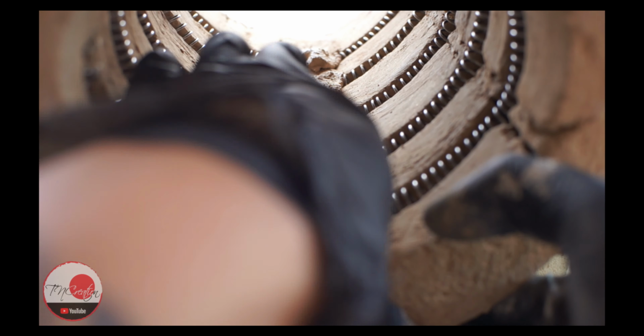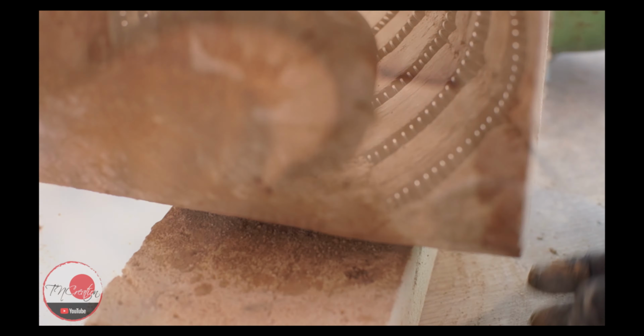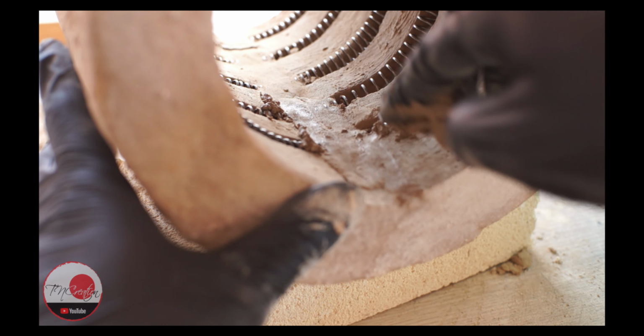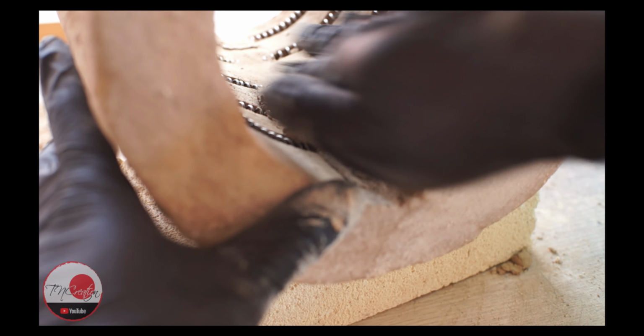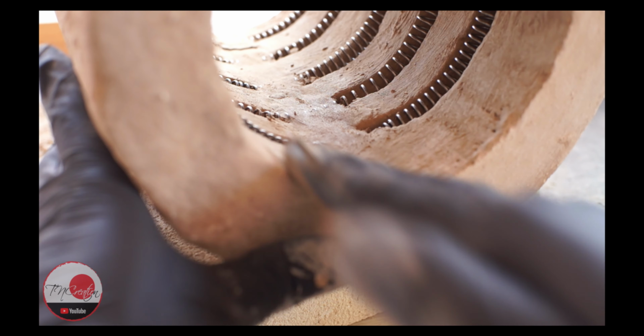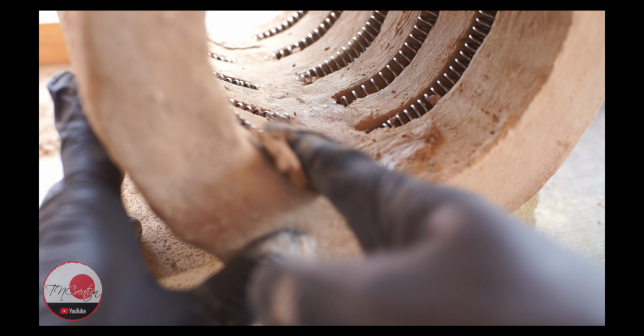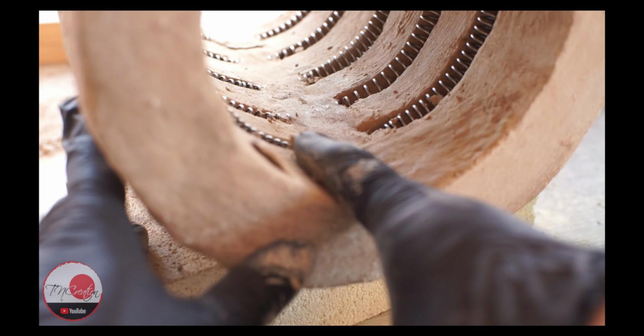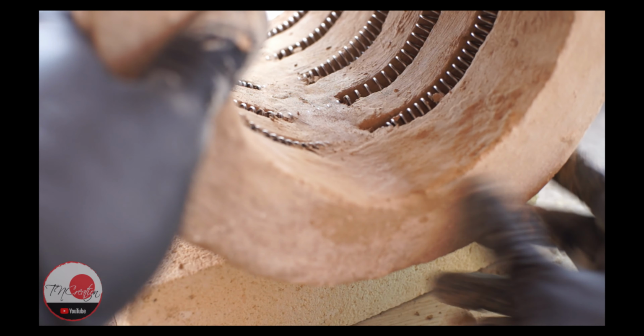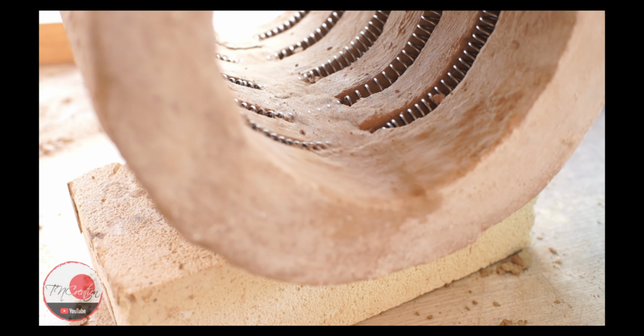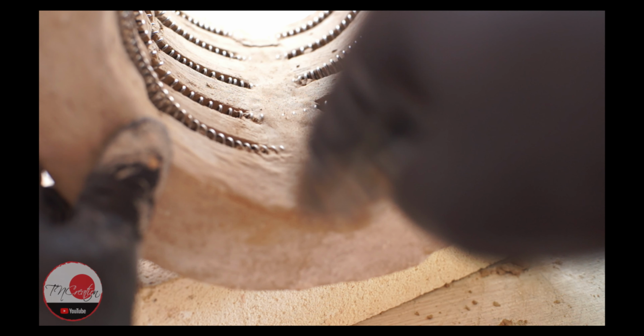Here is what I suggest you not to do like me. That is to embed the heating element with the refractory cement, like I did in this footage. The consequence is that the heating element will get too hot at the sealing point, and will break at a certain point. Normally when the kiln reaches 1800 degrees Fahrenheit, or 1000 degrees Celsius.